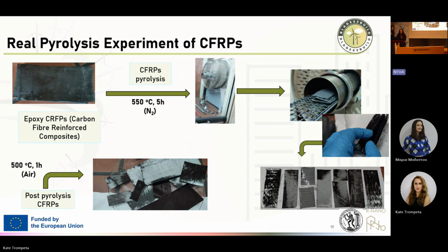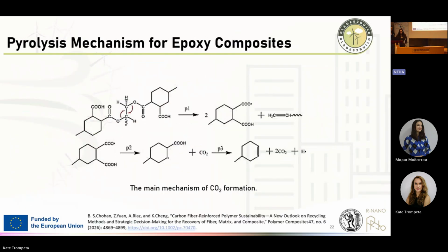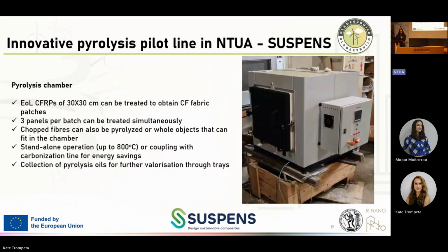In the chamber that we have designed, we are able to recover patches of 30 by 30 centimeters, because this is the internal chamber. So this means that we have a composite plate which is 30 by 30 with the fabrics at 0/90 degrees. We can reclaim the full length. In other cases, we can chop down, as you did in your work, to have just short fibers, and this depends on the shredding machine that we are using.